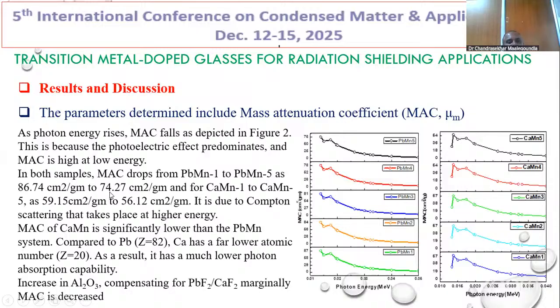from 86.74 centimeter square per gram to 74, sir. In the case of calcium also, it is decreasing from 59.15 to 56.12 cm2/gm. The main reason, apart from the mass of lead fluoride, is that the photoelectric effect plays a vital role. As the photoelectric effect decreases, the value of MAC also decreases. The maximum MAC value for the calcium oxide glasses is less than for the lead fluorides. But I am comparing with calcium fluoride, sir, because it is stable and non-toxic. That's why I replaced lead fluoride with calcium fluoride, sir.